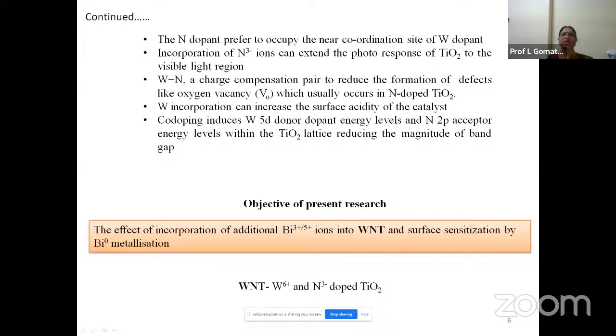Nitrogen dopant is preferred to occupy the near coordination site of tungsten. Incorporation of N3- ions can extend photoresponse of TiO2 to the visible region. And tungsten and nitrogen form a charge compensation pair to reduce the formation of defects like oxygen vacancy, which usually occurs when you dope nitrogen into the TiO2 lattice. The tungsten incorporation can increase the surface acidity of the catalyst. Co-doping induces tungsten 5d donor dopant energy level and nitrogen 2p acceptor energy levels within TiO2. The donor levels are present just below the conduction band, and acceptor levels are present just above the valence band. So with this brief introduction, I'll go to my next slide.